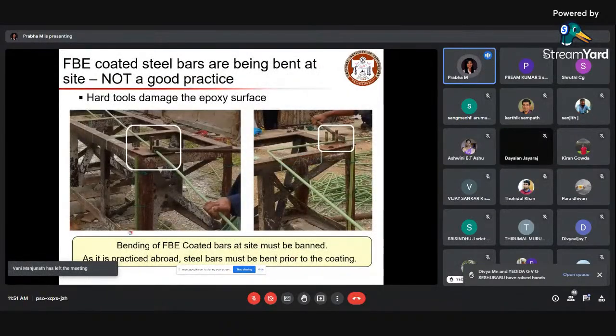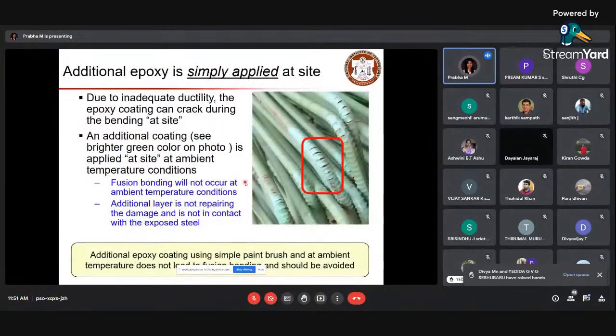Here are examples where such rebars are being cut and bent at the site, and while it is being done, the coating gets damaged. You can see here the coating got damaged, and a lot of cracks were observed on top of the coating.